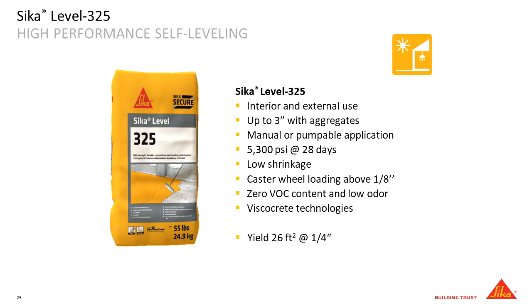5,300 PSI at 28 days, so you get an incredible amount of compressive strength with this after a month. Your typical concrete slabs are 3,600 to 3,800 PSI after 28 days. So this is an incredibly rigid and high compressive strength product.